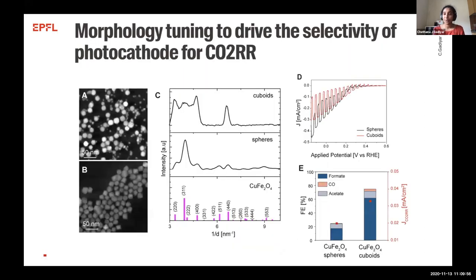And then what we wanted to do was to use it for an application. So we made the same size of copper iron oxide cuboids and spheres, and we checked the selectivity of these materials for the photoelectrochemical CO2 reduction reaction. It was interesting that in this case, the cuboids had higher activity towards photoelectrochemical CO2 reduction, as well as higher selectivity for formate in comparison to the spheres.